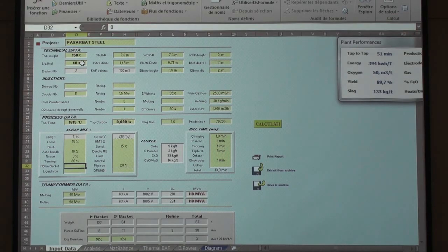Overall, what percentage of hot heel should you use when using DRI more than 90%? I would suggest 30 to 40%, yeah. When you have, let's say, a COS or a Consteel, then you need to go between 40 and 50%. There is some report, I don't know the exact values, but it's per hot-heel ton, we can save electric energy. How much?